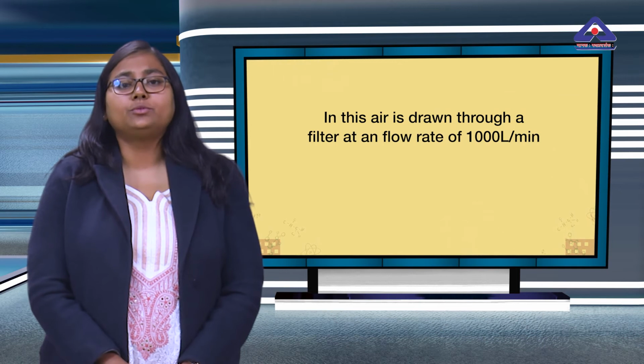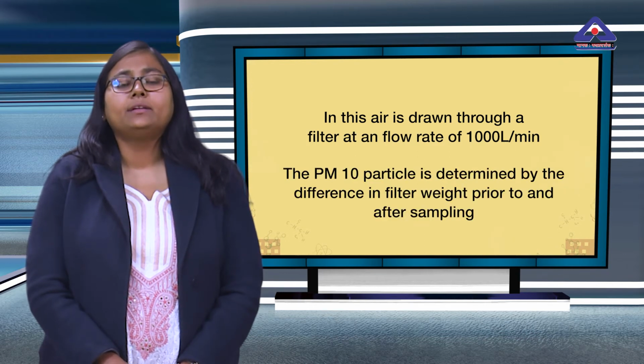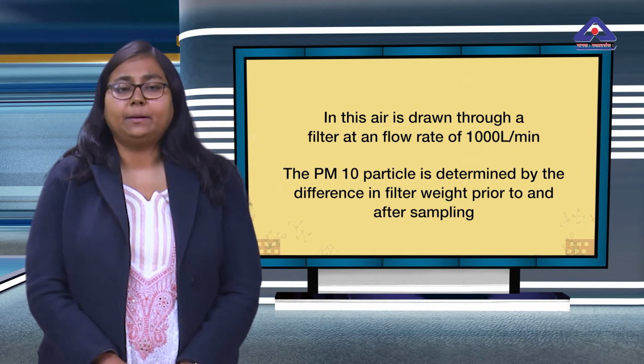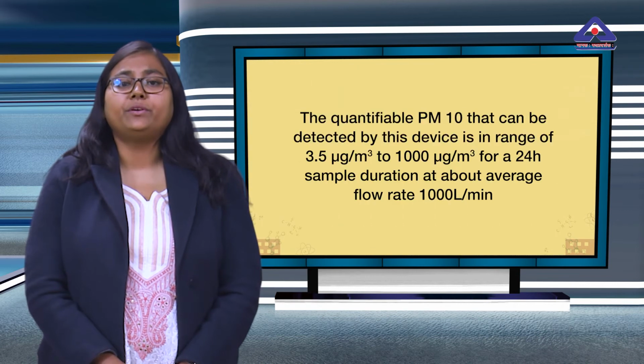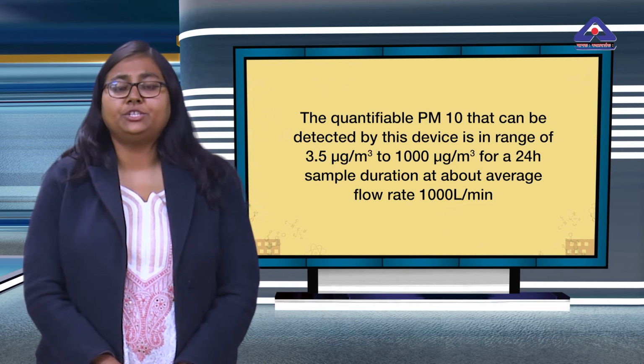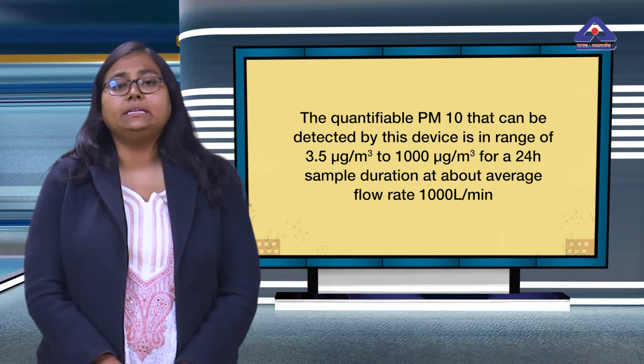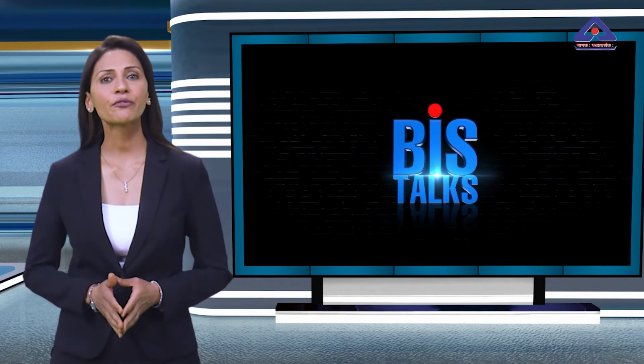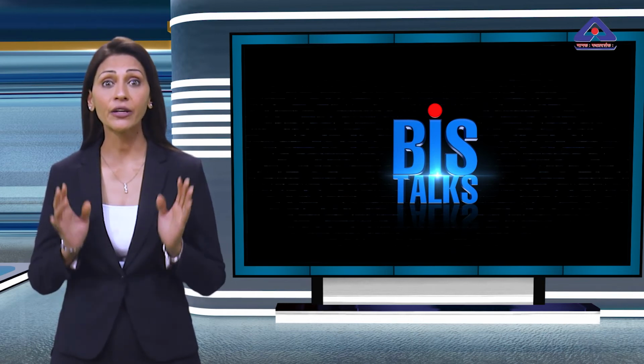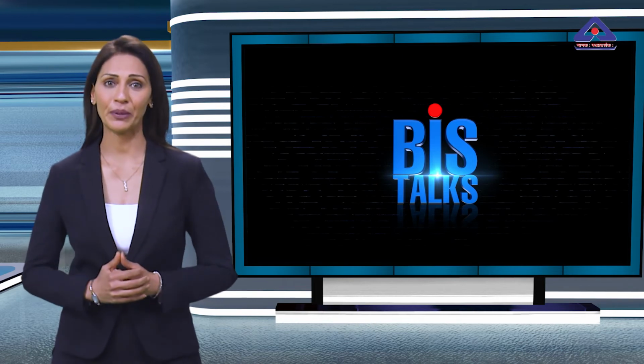In this, air is drawn through a filter at a flow rate of 1000 liters per minute. The PM10 particle is determined by the difference in filter weight prior to and after sampling. The quantifiable PM10 that can be detected by this device is in the range of 3.5 microgram per meter cube to 1000 microgram per meter cube for a 24-hour sample duration at an average flow rate of 1000 liters per minute. The quality of water serves an important role not only in drinking water but also for major industries such as steel, chemical, paper and pulp and many more which use water for their production. So let's hear from Ms. Shubhanjali Umrao how BIS standards are ensuring the quality of water being used for industrial purposes.